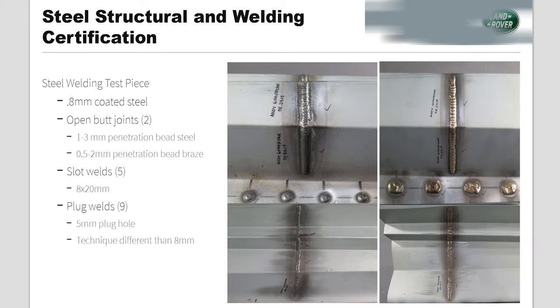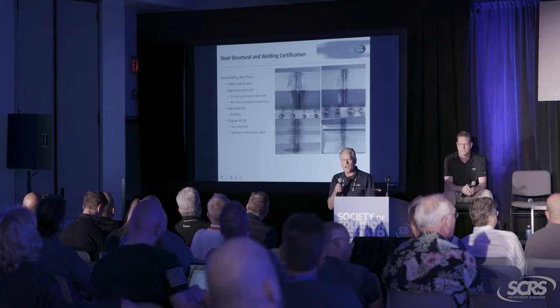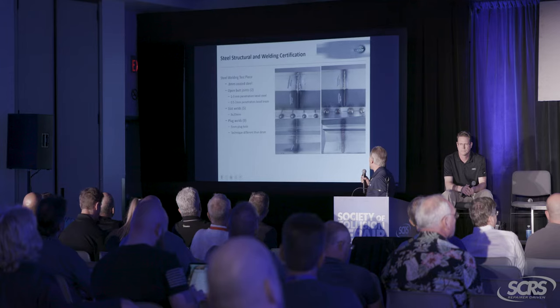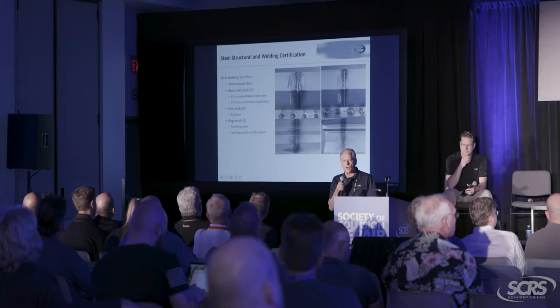On the steel side of it, just imagine the steel part looks like what you just saw in aluminum. And what I did is I got it a little bit closer for you, so I took pieces of it to show you. You're looking on the left side at an open butt joint done with silicon bronze MIG, okay? And what you're seeing on the left side, the upper one obviously is the outside of the weld, and the lower part is the photo from the inside of the weld.